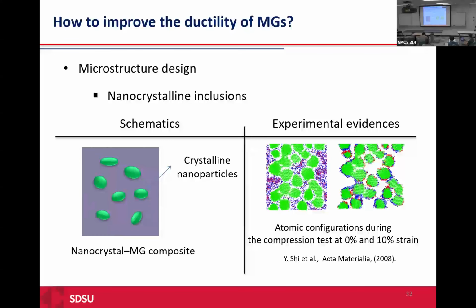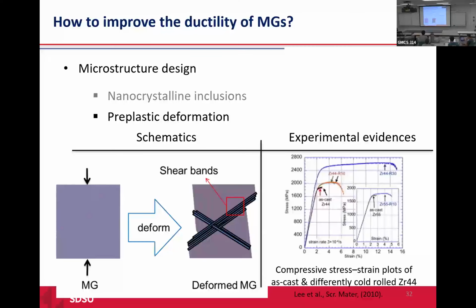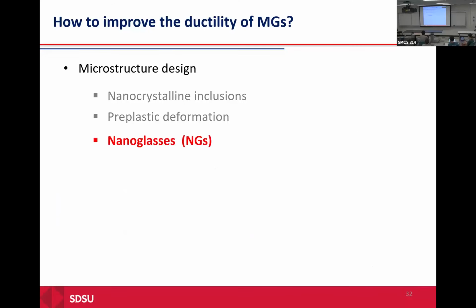One of the methods is using some nanocrystalline inclusion, like putting another type of element that can be used as a source for the nucleation of shear bands, and then distribute the shear band formation and give more plasticity to the material, or doing some plastic deformation and cold work just to distribute this shear band formation. Another one that I'm going to try is forming nanoglass material.